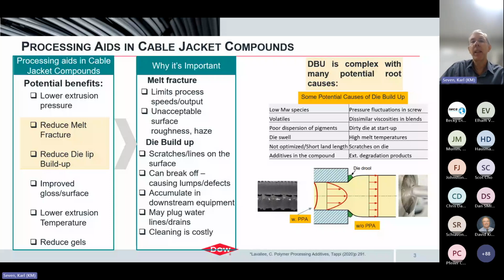I will highlight one example here. If you, for example, have a high component of low molecular weight species within the compound, either coming from the resin or even the additives themselves, or the combination of the two, under high shear stresses within the die, you can get a segregation effect. In other words, the low molecular weight species can get pulled off within the high stresses of the die and then deposit on the surface of the die. And so, that's one potential issue. Or, of course, the outside of the die is relatively cool. So if you have a high amount of volatile components within your compound, they can, of course, condense out on the surface of the die.